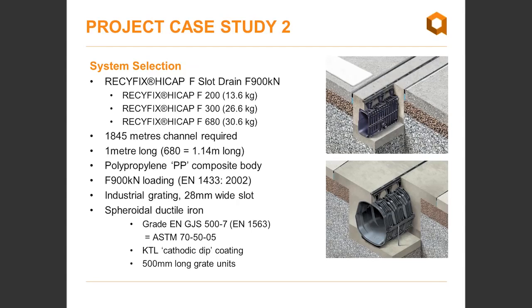Polypropylene composite body, again UV stable with carbon black added. F900 loading, and the grate was a ductile iron grate. We supply these grates with a KTL cathodic dip coating, which is a special coating that we supply standard with this unit, which is very good for this area because it's again corrosion resistant. And the slot width is 28 millimeters.